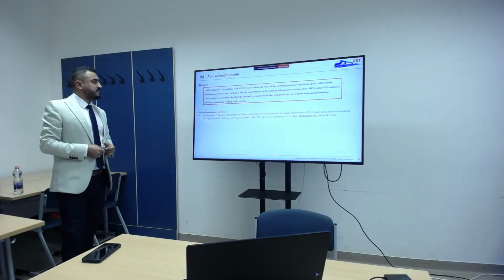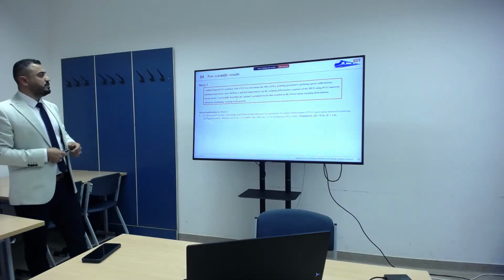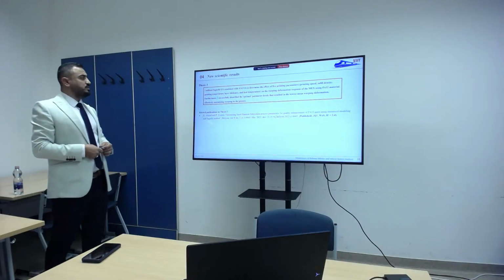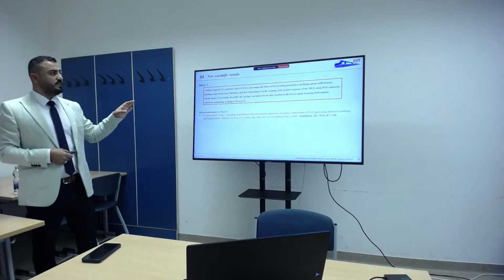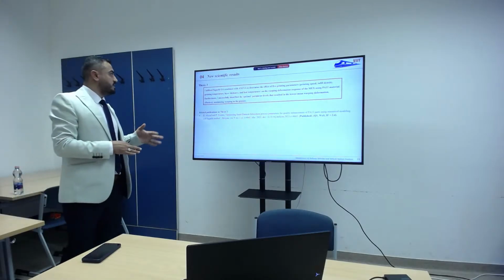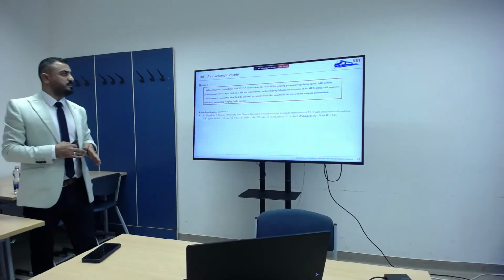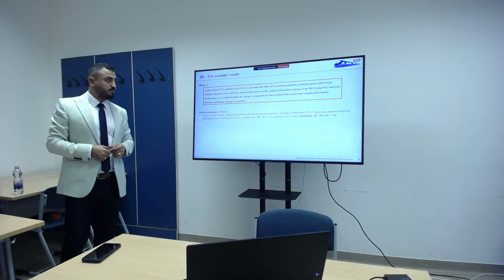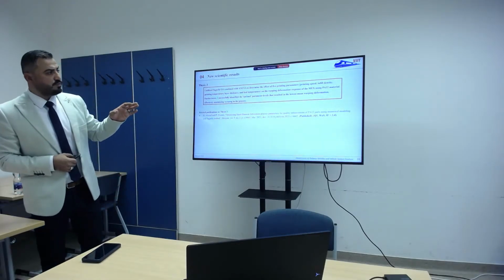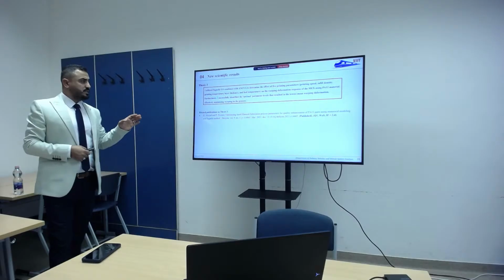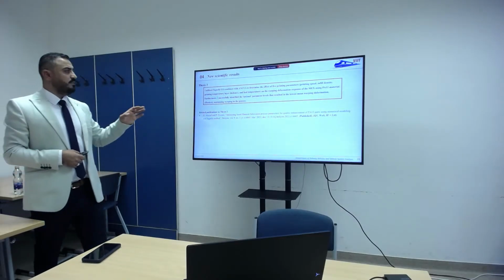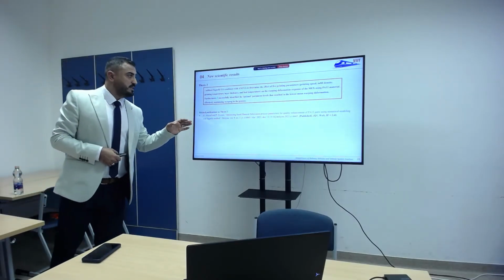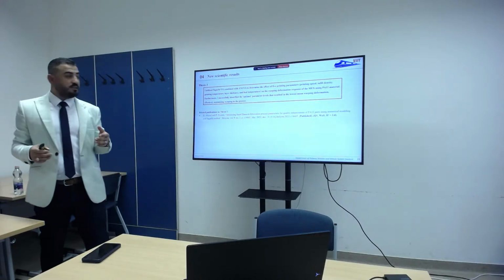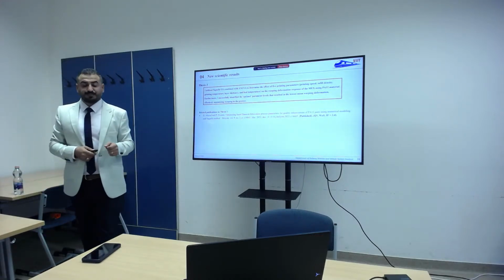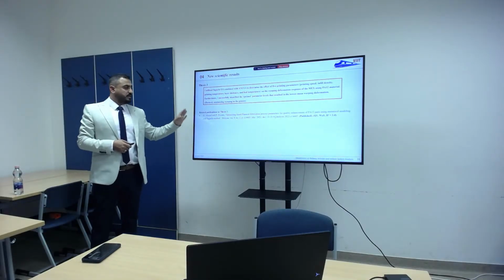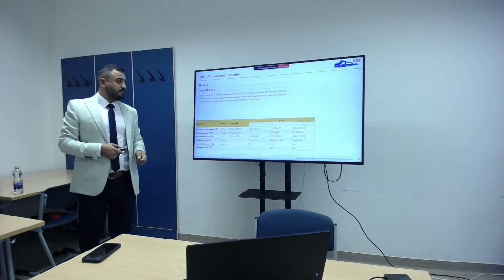So, thesis number 3 stated that I utilized the Taguchi orthogonal array combined with ANOVA to determine the effect of five printing parameters: printing speed, infill density, printing temperature, layer thickness, and bed temperature, on the warping deformation response of the material extrusion using PA12 material. Furthermore, I successfully identified the optimal parameter levels that resulted in the lowest mean warping deformation, effectively minimizing warping in the process. And I will publish my results in a Q1 journal article.